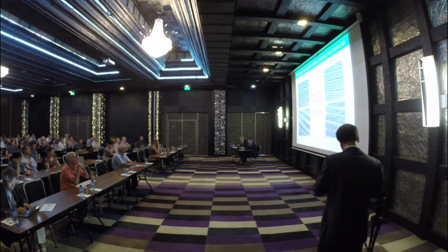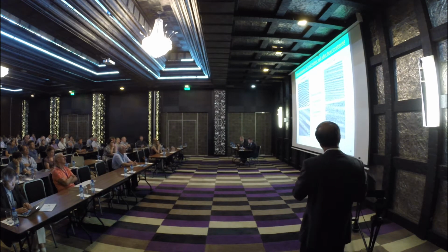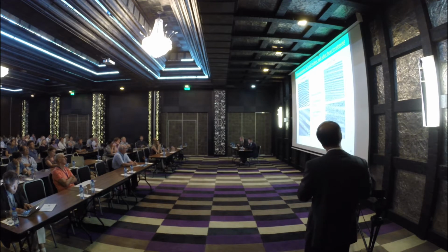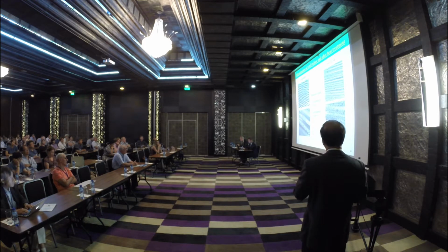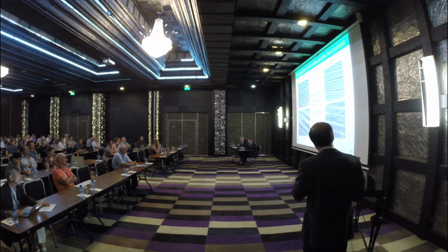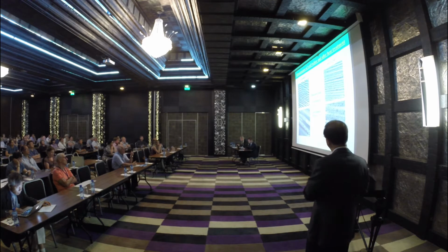And the microstructure observation was also performed in the left-hand side. This is the anodized tip and microstructures at high magnification. We can see that the wall, this is the wall of the AO. The thickness is about 53 nanometers average, and the tunnel or the pore size is around 33 nanometers.